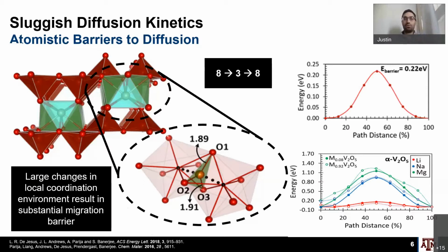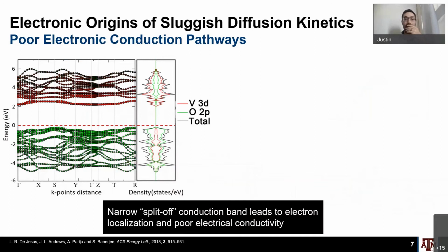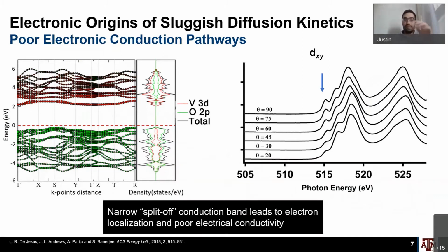But then on top of that, what we also have to consider is, as the lithium ion moves through the lattice, because of the poor electrical conductivity, there's also a barrier to electron diffusion. And in the case of V2O5, where that really comes from is that it has this narrow split-off dxy band, and so you can see that here in the density of states. And so this sort of narrow band leads to repulsion of the electrons, so we get splitting into an upper and lower Hubbard band that takes place. And so we don't really get improved electrical conductivity as we pump lithium into this material.